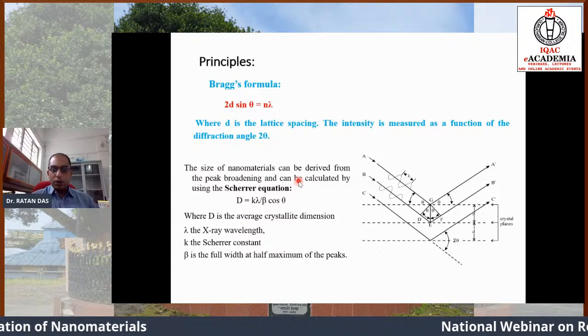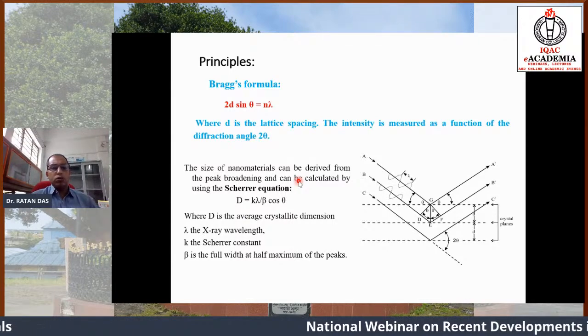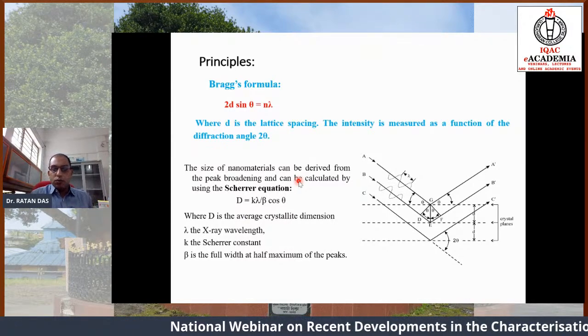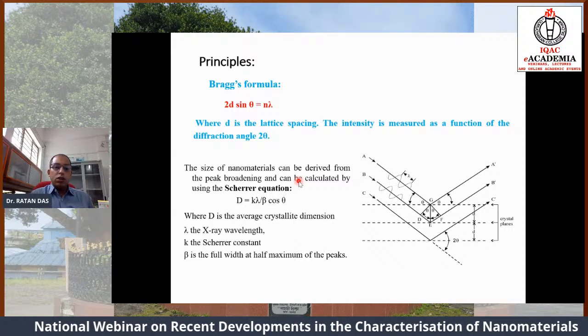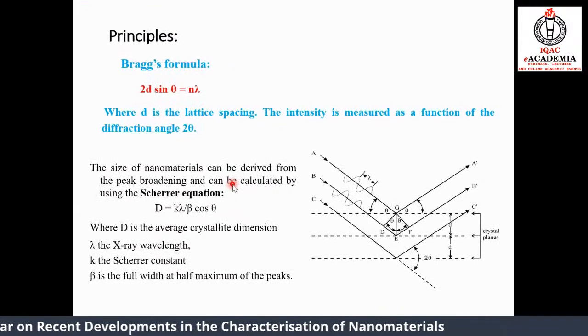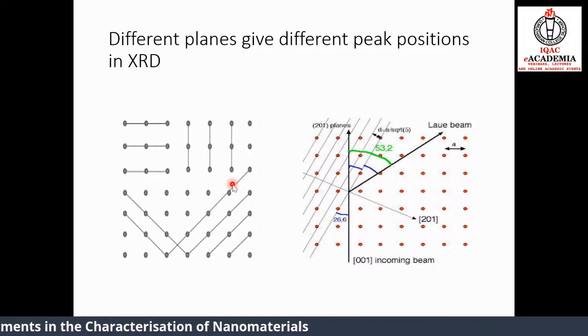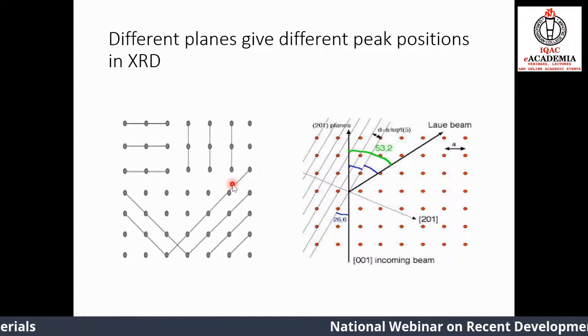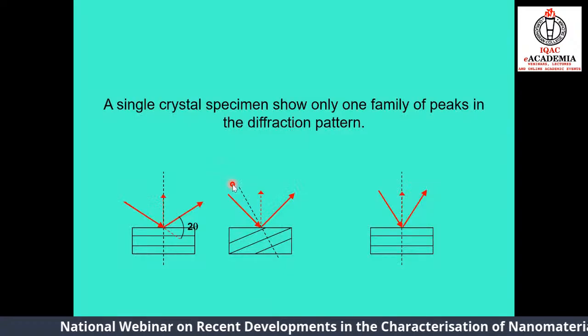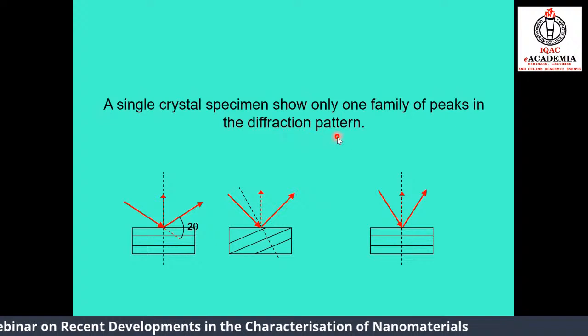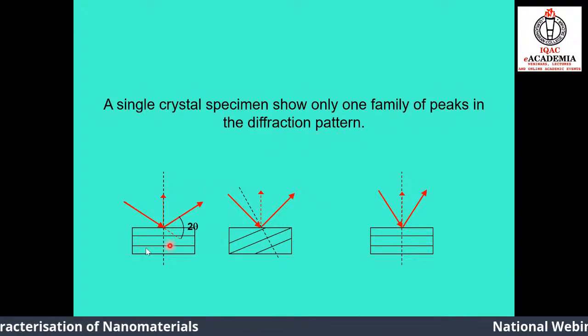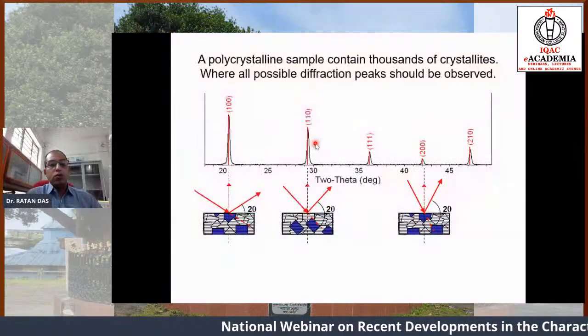I shall explain it in my subsequent slides, but beforehand I want to introduce this Scherrer formula because it is very important in calculating the size of the nanoparticle in the X-ray diffraction pattern. So what I want to say is that the different planes present in the sample provide different diffraction peaks in the X-ray diffraction pattern. A single crystal specimen shows only one family of peaks. I mean this is a single crystal with one set of planes, and it will provide only one particular peak.